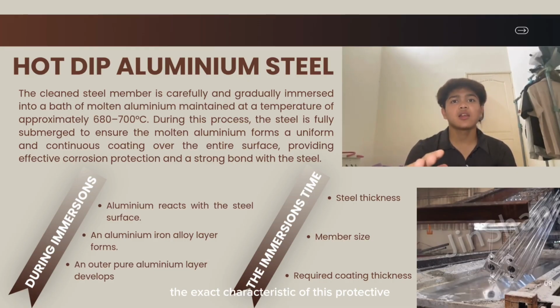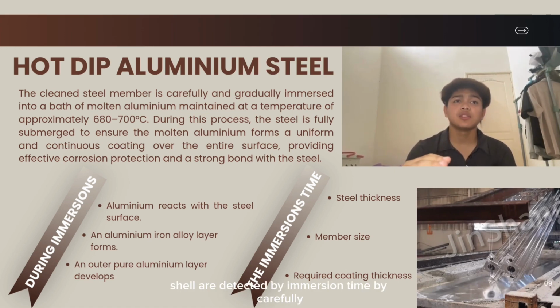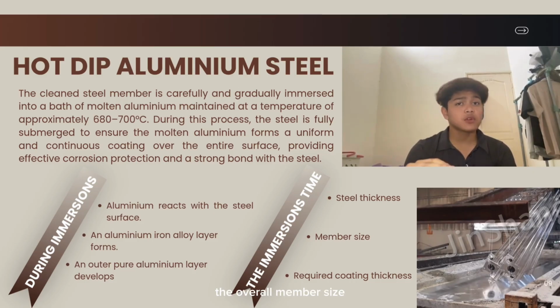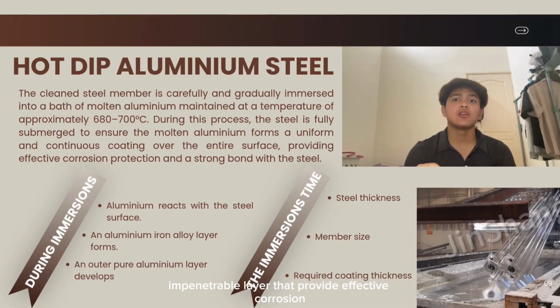The exact characteristics of this protective shell are dictated by immersion time. By carefully calibrating how long the steel remains submerged, calculated according to the steel thickness, the overall member size, and the required coating specification, we can tailor the final result perfectly. What remains is a seamless, impenetrable layer that provides effective corrosion protection and a powerful metallurgical bond.